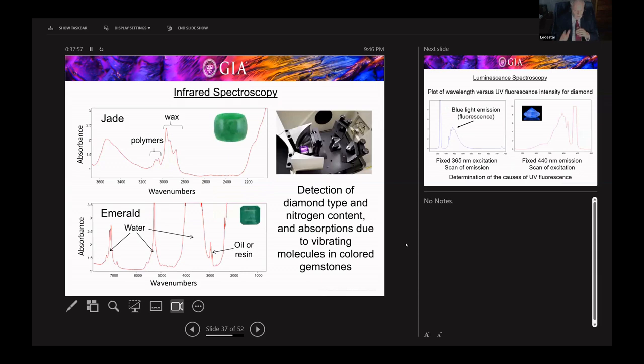We also use infrared spectroscopy, which is very valuable for detecting type 1 or type 2 diamond and nitrogen content. But we can also detect molecules vibrating in the gem material. So at the top, this is just a jade, and it's got some polymer and wax absorption features. Those are materials that are put into the jade to make it look better.